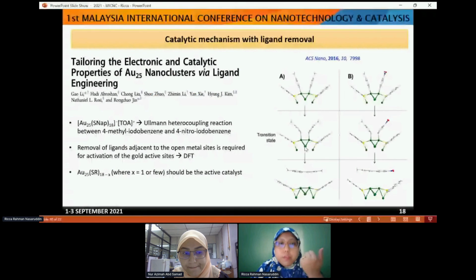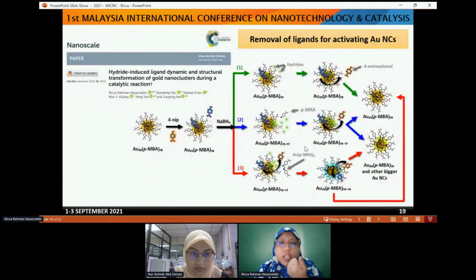This is an example of a previous study that mentioned removal of ligand is very important in order to activate this gold nanocluster catalyst. We also performed this study to understand the effects of ligand removal on the catalytic activity and also the structural transformation. What we realized is that when the hydrides bond to this atom, it opens more of the active sites to the reactants. Because of that, we can have higher catalytic activity.